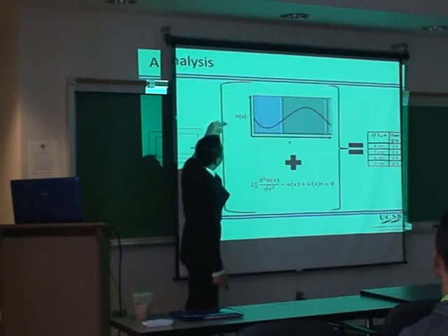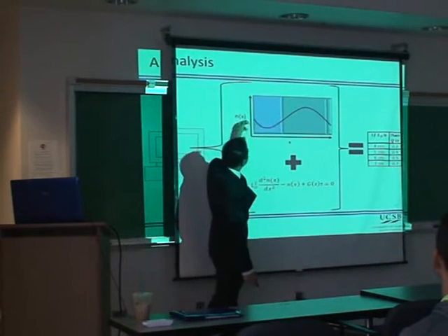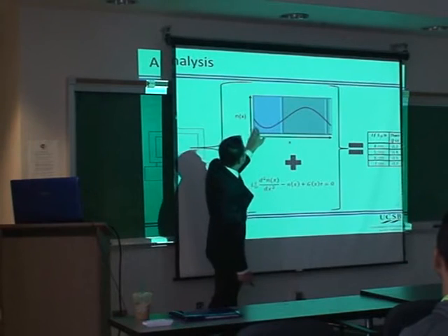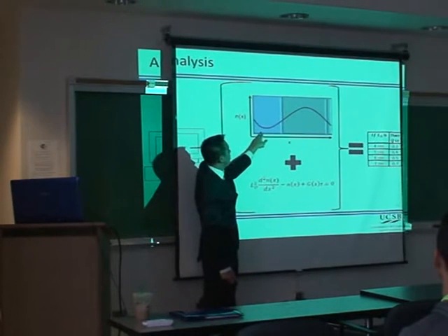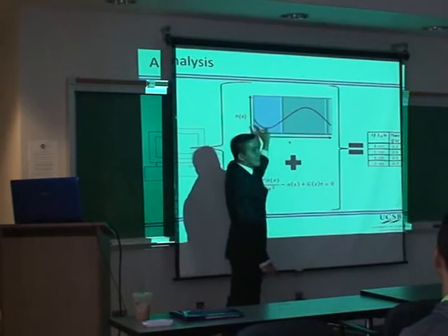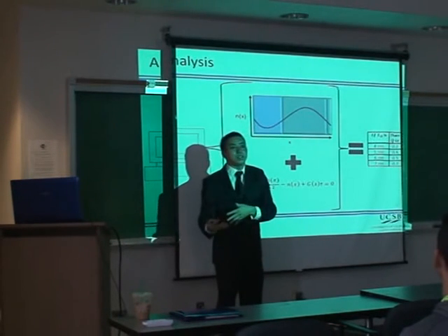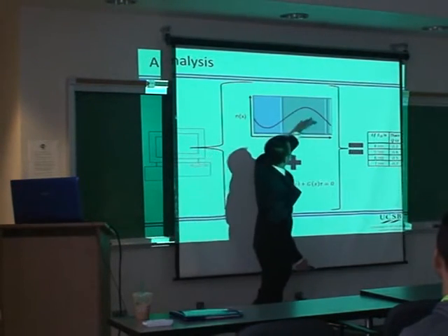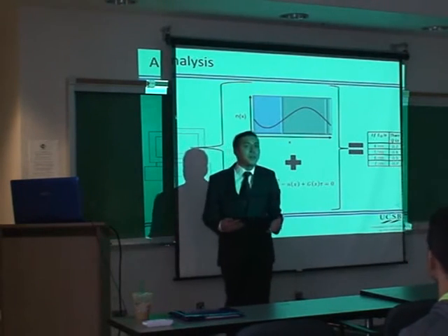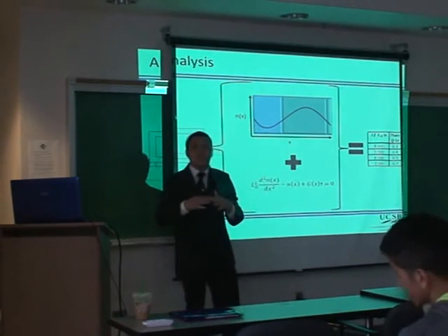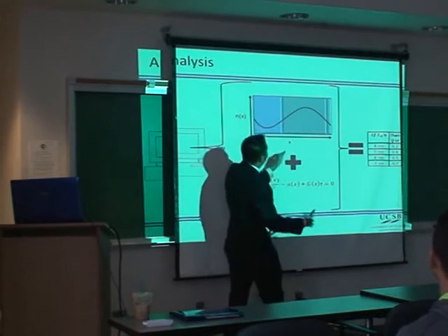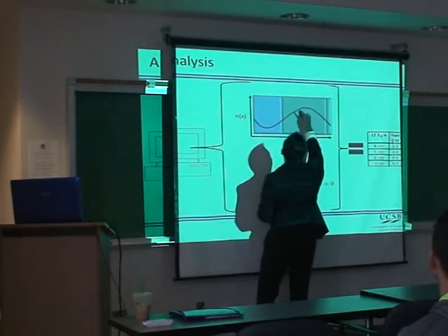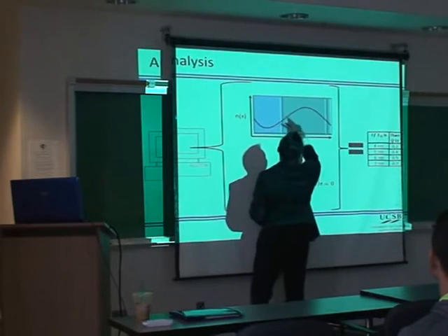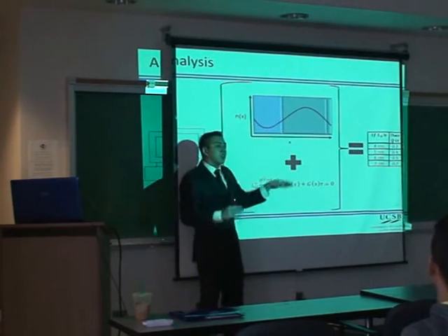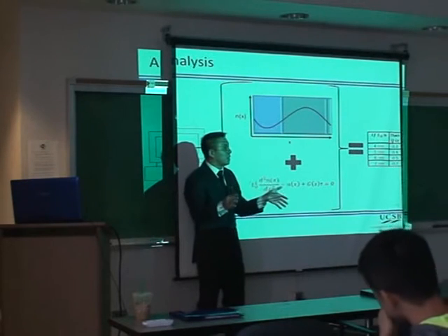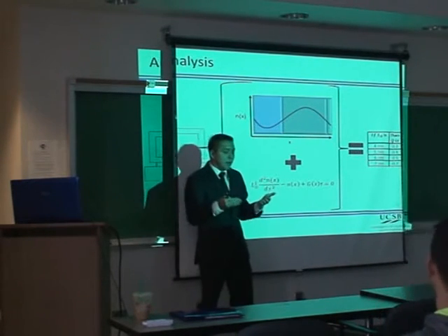And the reason is because as light enters this film, it actually gets reflected at each interface, because there's a difference in index of refraction of each of these materials. And it actually reflects onto itself, so it can constructively and destructively interfere with itself, creating these patterns. Further, that optical field could be absorbed by the organic material, decreasing the field. And then finally, with that absorption, you create this absorption profile or exciton density here. And this is kind of like the initial condition, the initial population of excitons. And what we want to see is what's going to happen now.